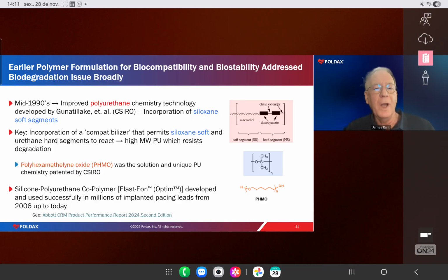And they found a way to incorporate, and again, see the cartoon on the right-hand side. It's not so important for our purposes. We got hard segments and soft segments, with the blocks for hard, meaning rigid, and the squiggly lines for soft. Found a way to couple soft segments, siloxane soft segments, with polyurethane segments.